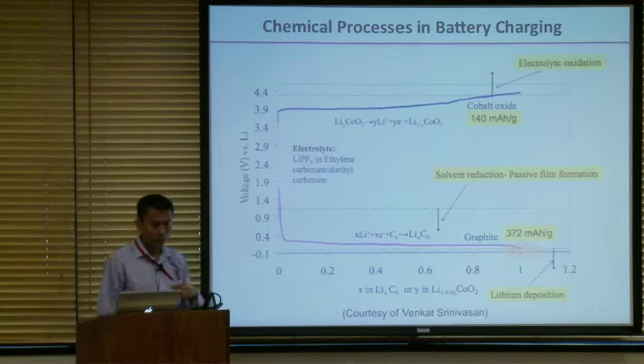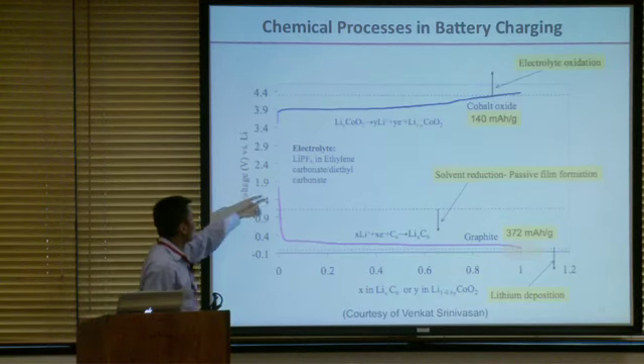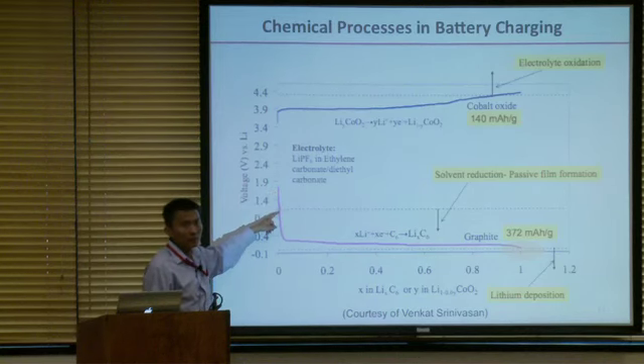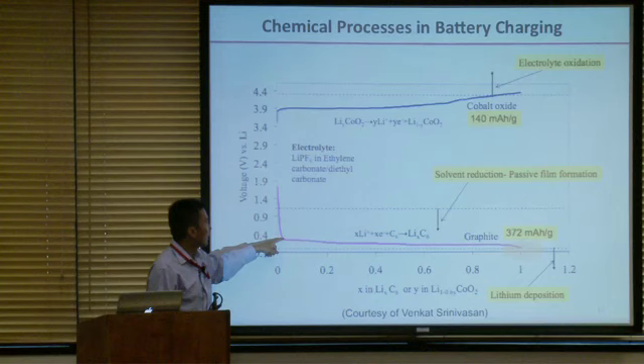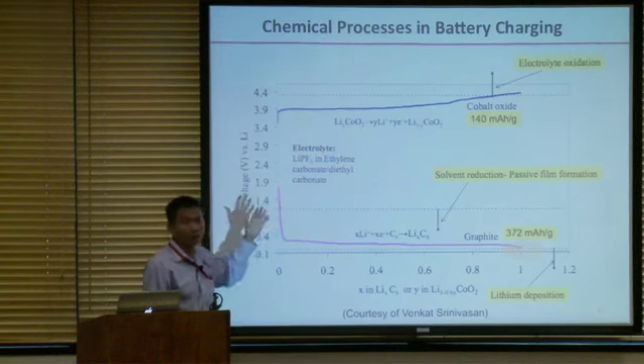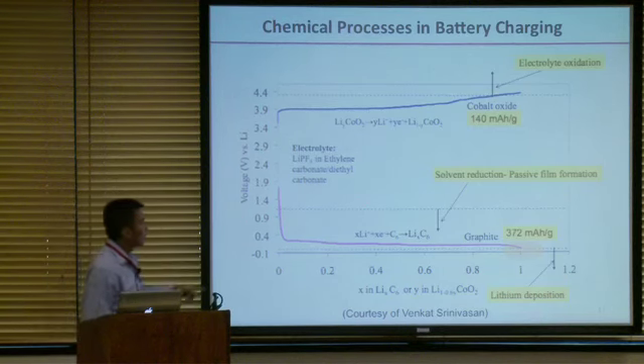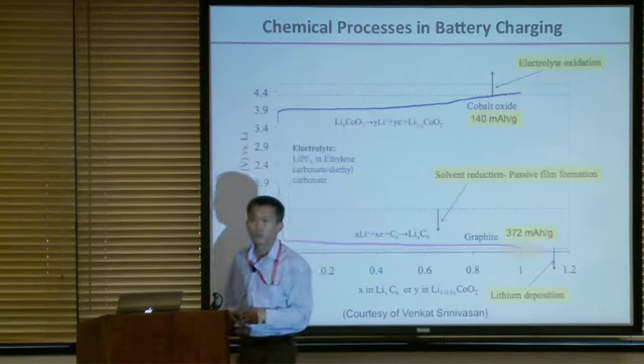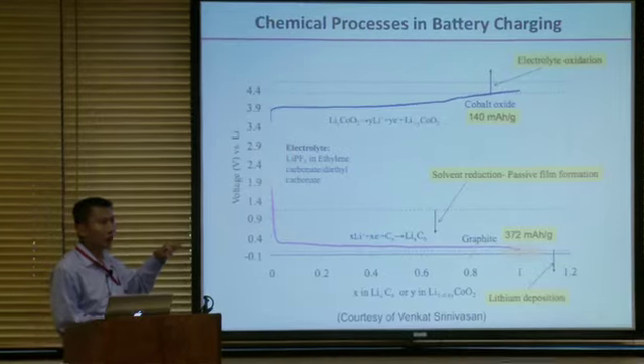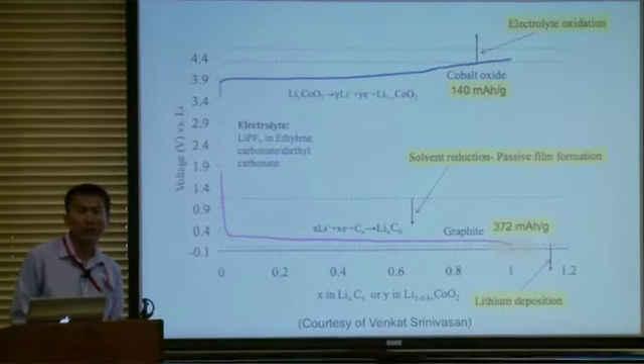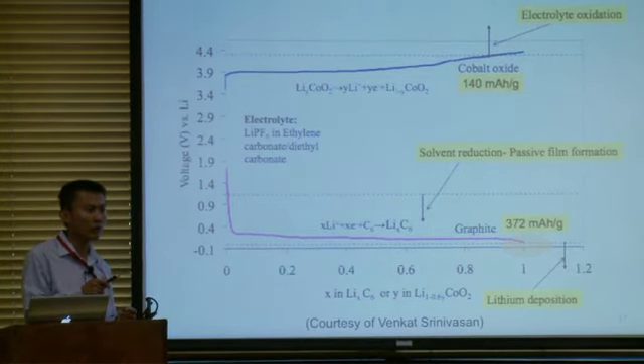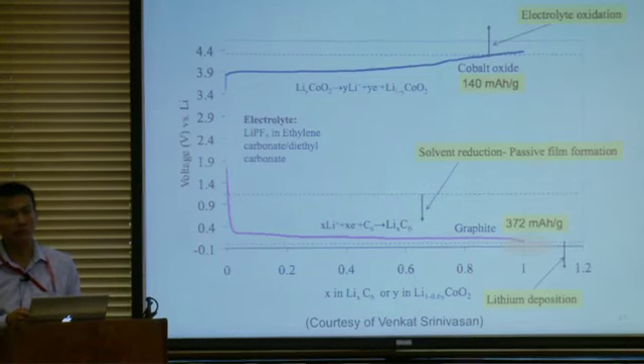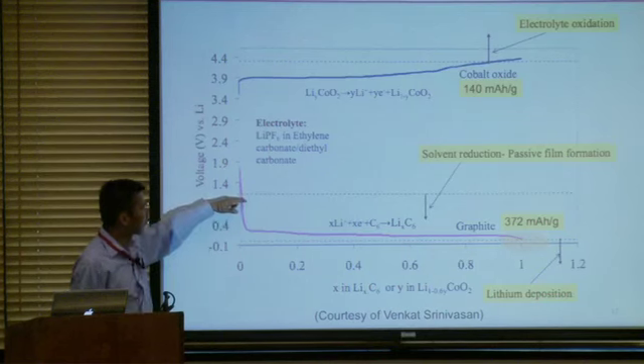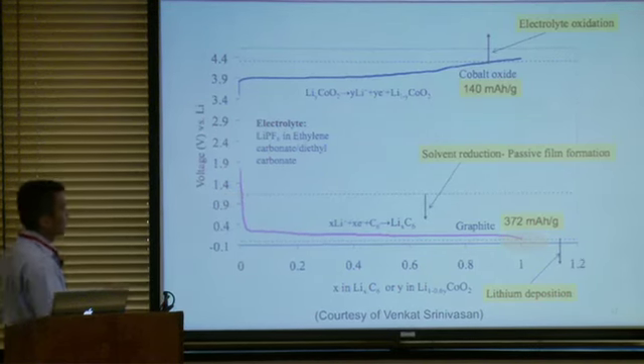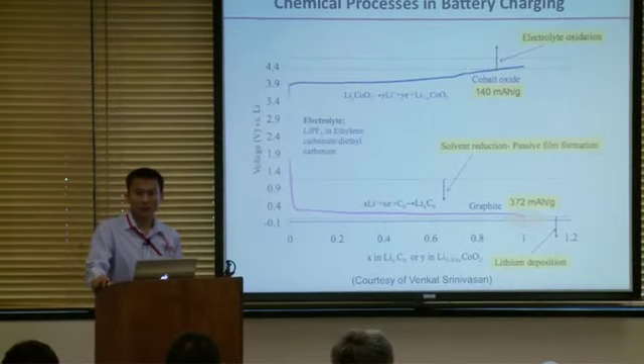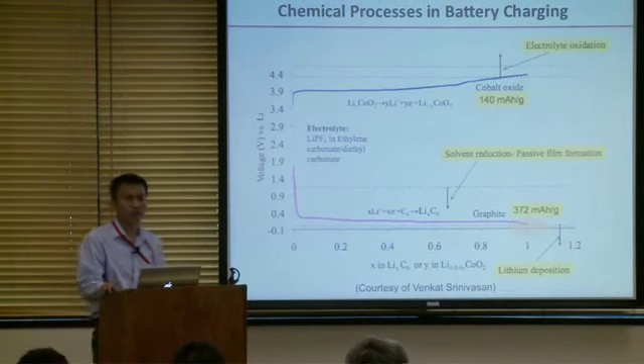Once you put lithium into carbon, the potential drops in the carbon, that's the negative side. And then it's going below roughly around 1 volt, somewhere around there. Side chemical reactions happen. You use organic electrolyte. We know once you get a potential of a material lower, it's so reactive. You look at lithium metal, you put lithium metal in contact with most of the materials in the world, lithium is going to react because lithium likes to give electrons away. Once you put the potential lower, this electrode will like to give electrons away to the solvent and the battery electrolyte. You start to build a film or passivation film right there.